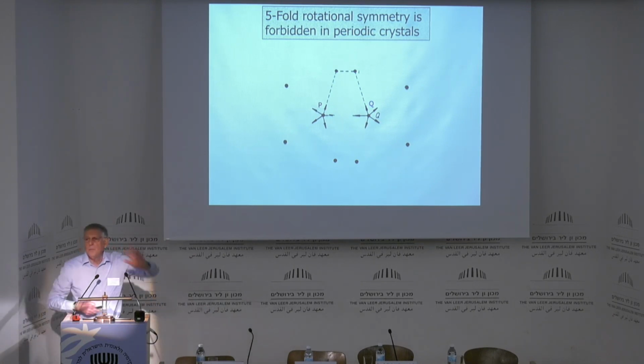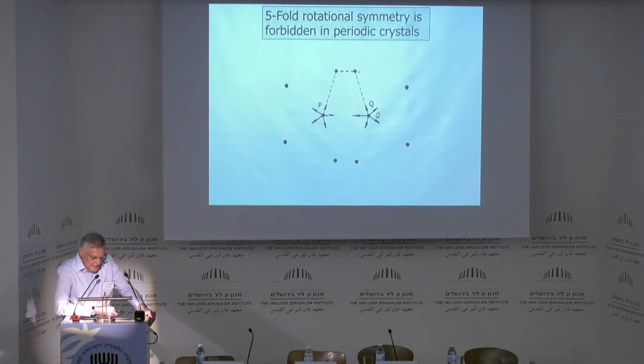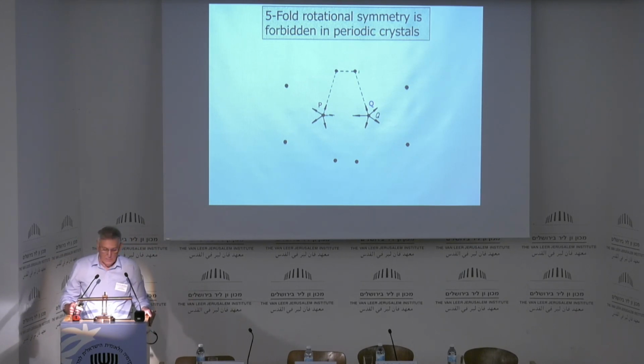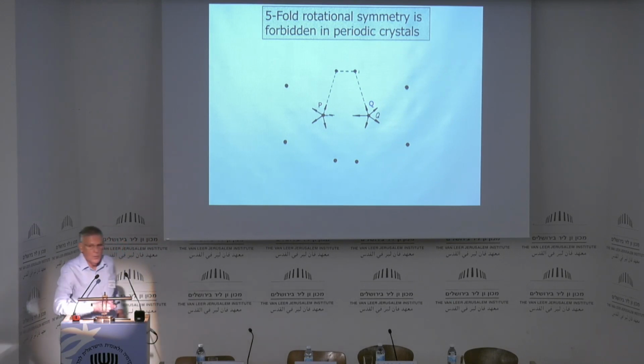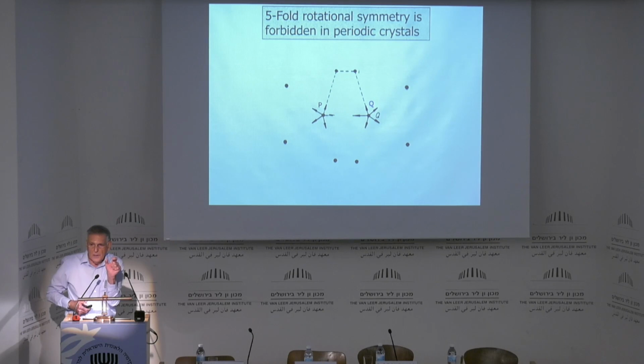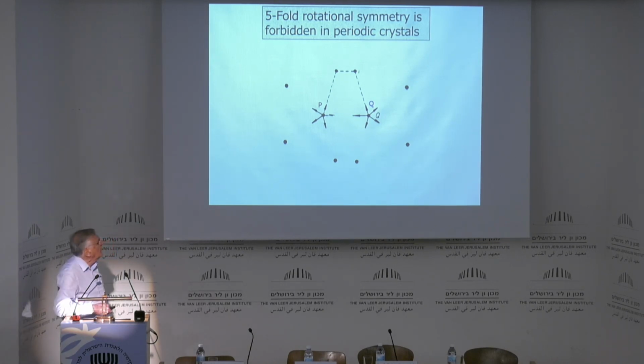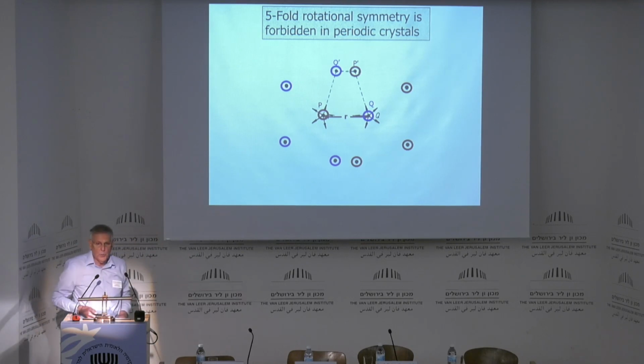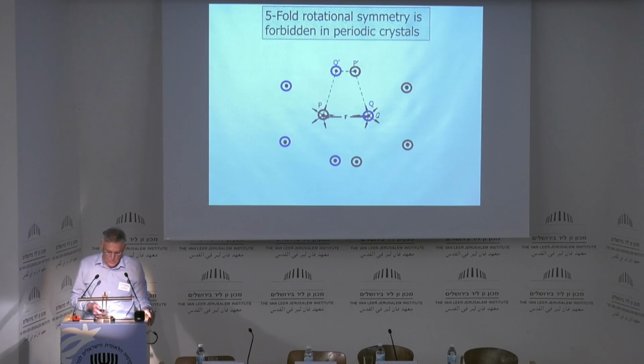And in order to prove it, there are many proofs. You can prove it many ways, but here is one proof which I like. Let's say that there is 5-fold rotation symmetry in periodic crystals. If so, let's take a plane in a periodic crystal in which you have 5-fold rotation symmetry, and choose 2 atoms, P and Q, and choose them in such a way that they are the closest atoms on that plane. Now, if 5-fold rotation symmetry is allowed, and the distance r is the minimal distance, then you can take atom Q, which is right here, and start rotating it around P. 1, 2, 3, 4, 5, and there must be a Q prime atom there, if there is 5-fold rotation symmetry. Same with P, 2, 3, 4, 5, and there must be a P prime atom there, but you see that P prime, Q prime are closer than PQ, which cannot be because I chose the shortest distance. Okay, simple proof why 5-fold rotation symmetry is forbidden.